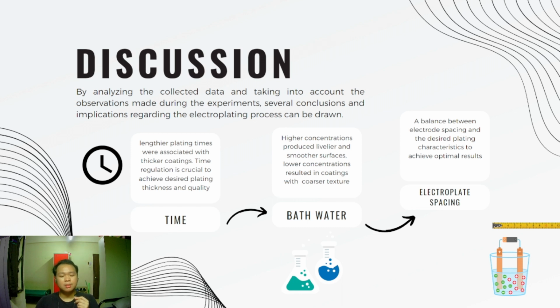The second one is bath water. We have used two types of electrolyte, which are copper sulfate and Coca-Cola. The recorded data showed that these two electrolytes do achieve electroplating. So it does work with Coca-Cola. However, copper sulfate has proved to provide a much more discerning result as compared to the Coca-Cola water bath. Coca-Cola provided a more contaminated and non-uniform coating result.